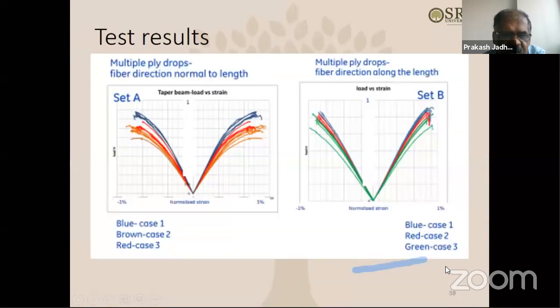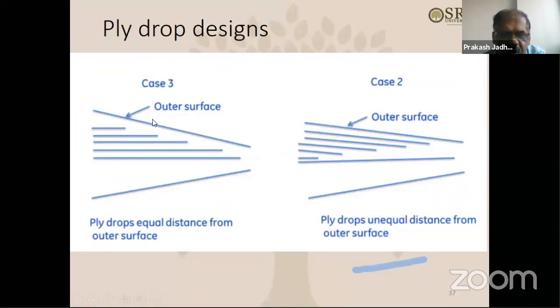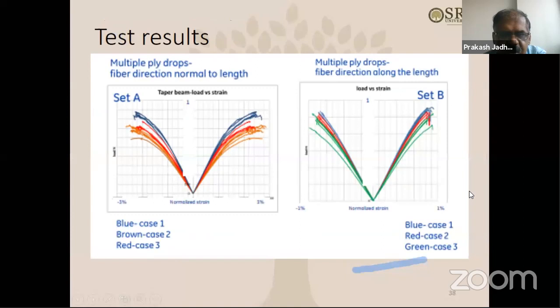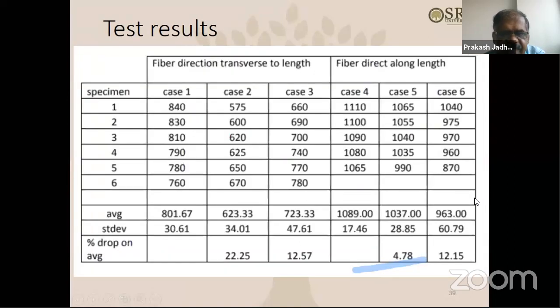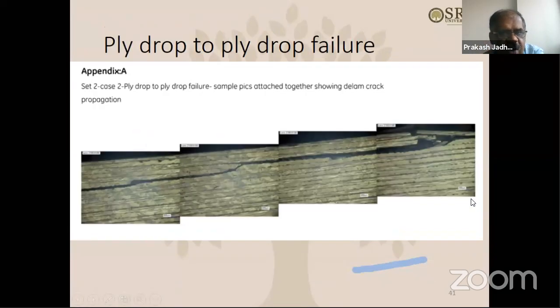Because you remember what I showed here. So as you can see, either they can jump from ply drop to ply drop, or they can jump here also, ply drop to ply drop and go to the surface. So all the cracks initiate somewhere near the ply drop, and then they have a tendency to go to the surface. So they have a tendency to propagate to the next ply drop so that they can go to the surface like this. This is what is interesting that is happening there. Like this, yeah, this is what I showed you.